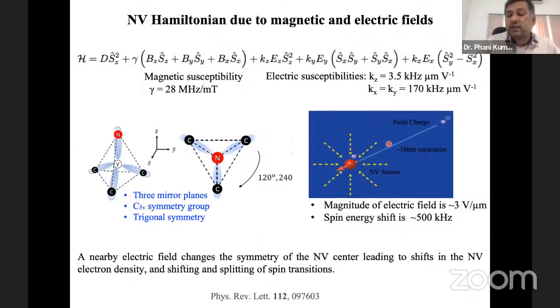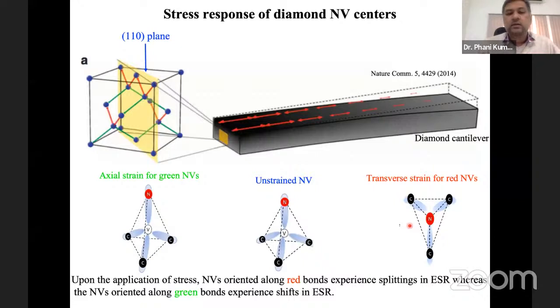You can see that even if you have a charge separated by 10 nanometers, the spin energy shift is only on the order of 500 kilohertz. This is much smaller compared to the magnetic susceptibilities we have seen in the previous slide. So it becomes tricky and challenging to measure these small electric fields, although it has already been demonstrated even from a single charge. Most of my studies during my postdoc and also here in Bhopal are focused on how we can measure the stress response of these NV centers.